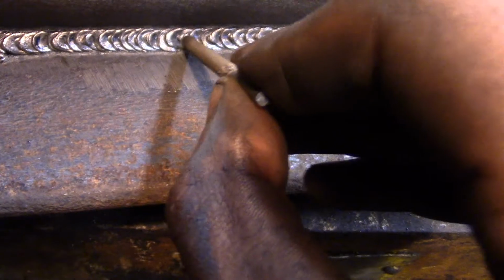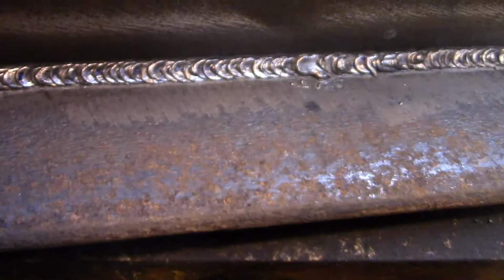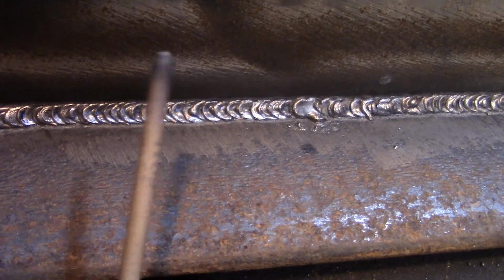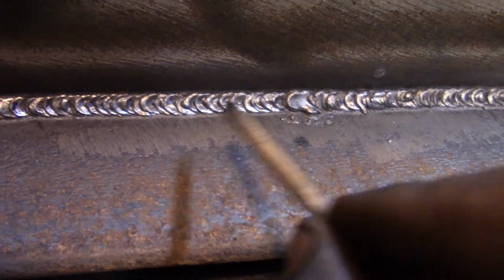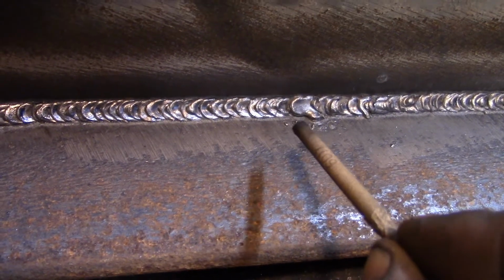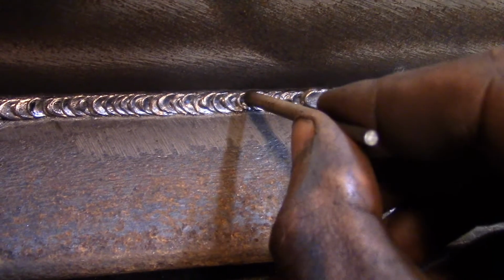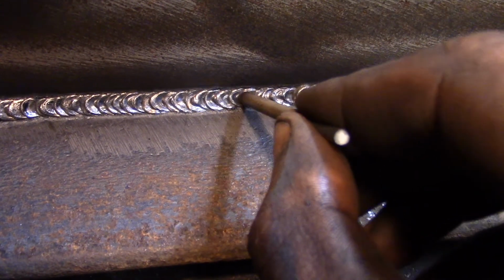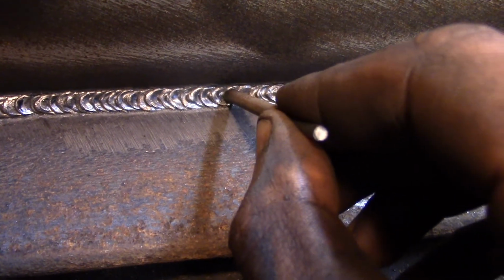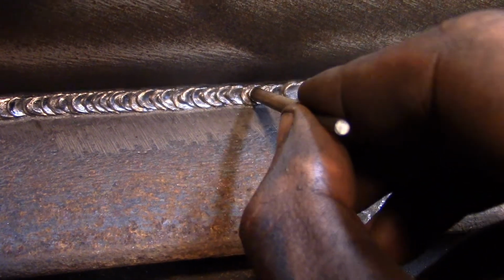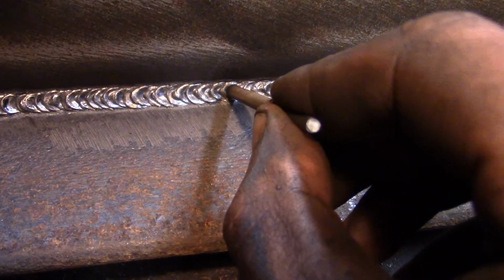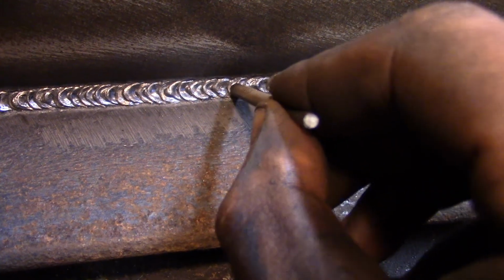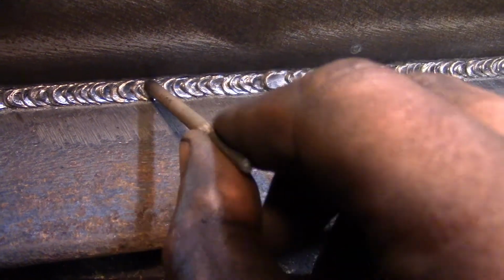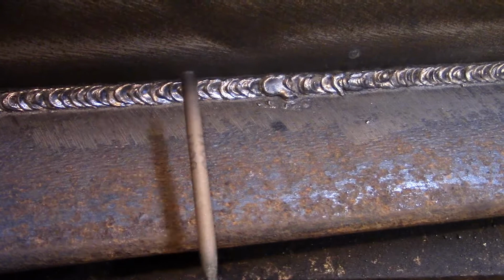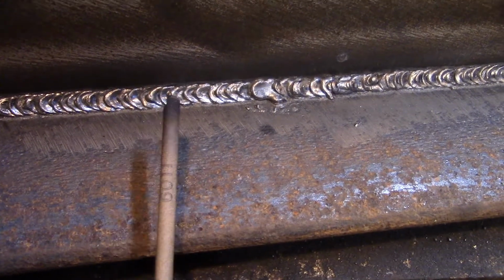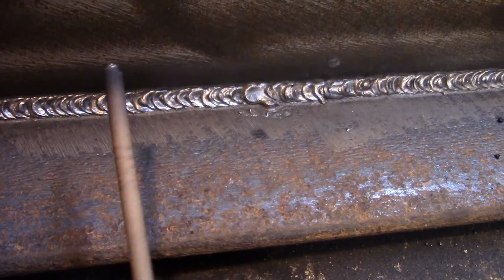And that's what gets these distinct ripples. That's also what allows this rod to freeze, because when you whip away from your main puddle, it freezes. So here's your main puddle, you whip away, it freezes, and then you come back to here and make that puddle. Then you whip away, that freezes, and you come back to there. Whip away from that puddle, it freezes, come back to there. That's how you can weld overhead and vertical and everything with this rod and not have it rain lava on you.